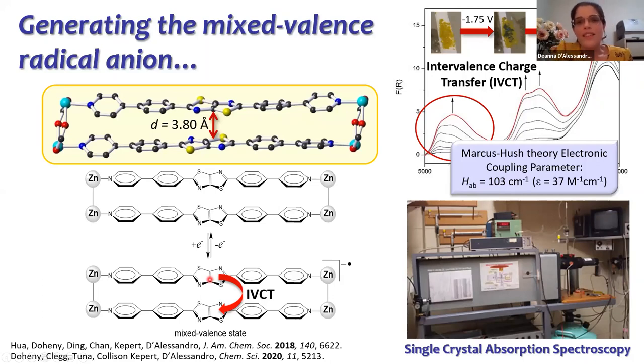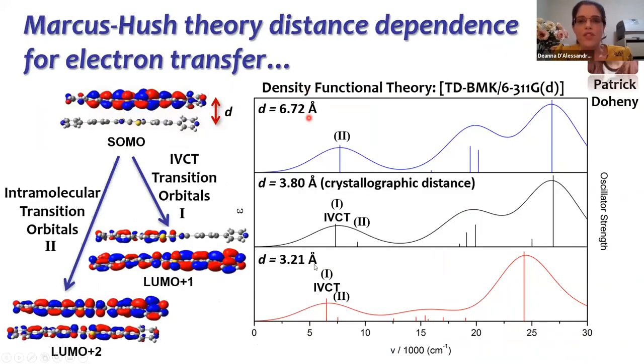We can also play this game computationally. So here we do the experiment where we either push the two ligands further apart, just over 6 angstroms, or we squash them further together to around just over 3 angstroms. And what we find here is that this near infrared band has two components. In the real compound here, we see one is an intervalence charge transfer band, which is due to predominantly charge transfer from the radical anion ligand to the formerly neutral ligand. And the other is an intramolecular transition.